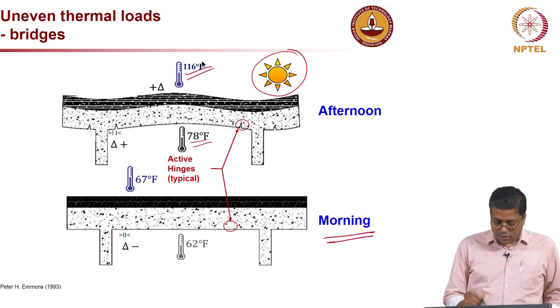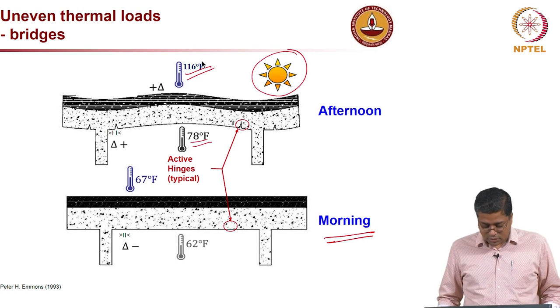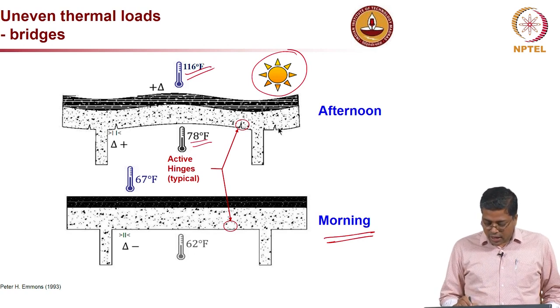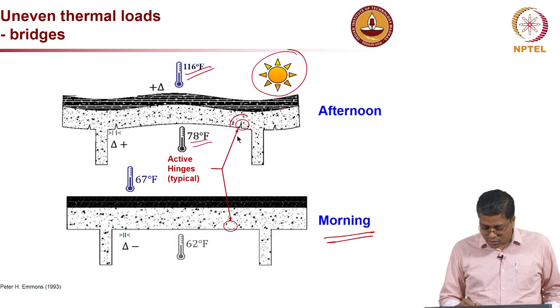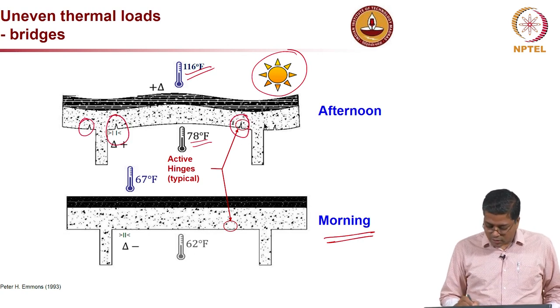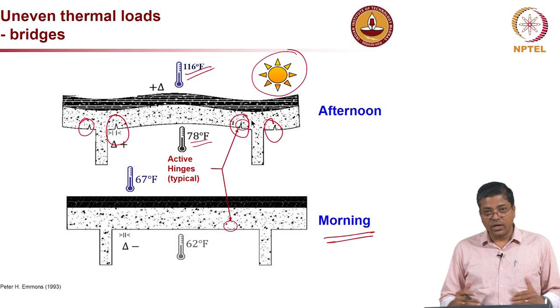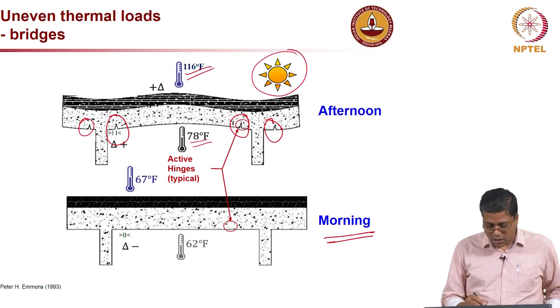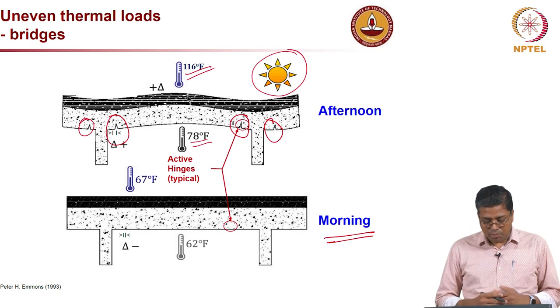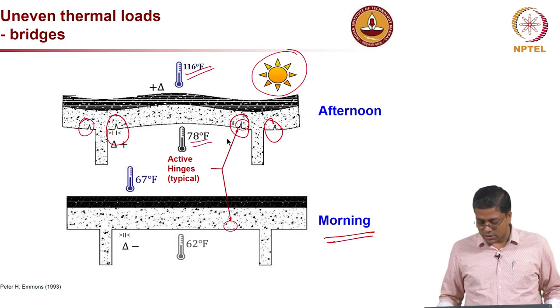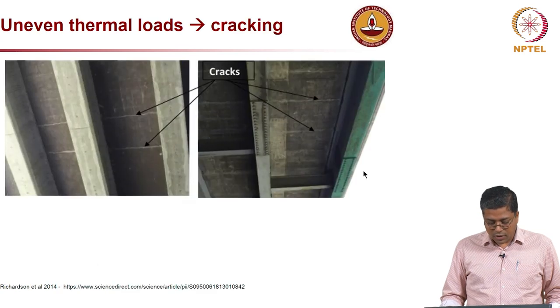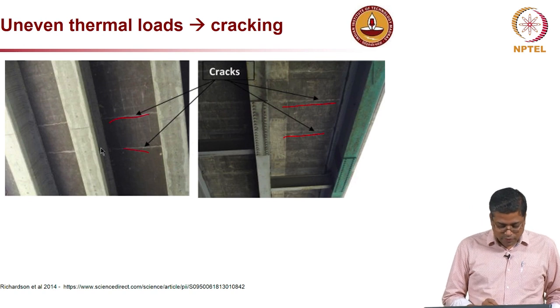Now, make sure this is not in Celsius, so please note that it is in Fahrenheit. And now you see that where the concrete is trying to change shape, it induces some cracks like this. You can see at the bottom here, wherever there is flexure happening, and because of the shrinkage or expansion of the top surface, there is some kind of buckling which is happening, and which induces this type of cracks. Now, this is a demonstration of such cracks, which is visible at the bottom of this bridge deck here.